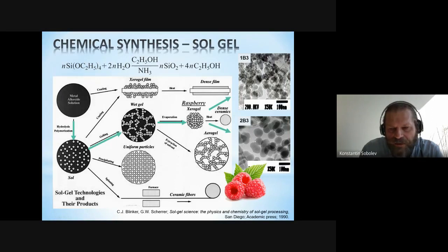Obviously, you can produce dense ceramics by further sintering, and of course, for concrete applications, we would rather use products that are as dispersed as possible. You have another way to produce aerogels, and from aerogels you can also produce very good particles. But again, if you still use the way to remove the alcohol and filter the particles out of the solution, basically dilute and substitute the alcohol with water, you can produce a direct dispersion of the sol in water with very little alcohol, and you can further use this in applications with cement-based materials.